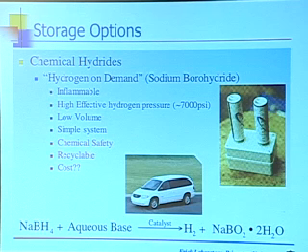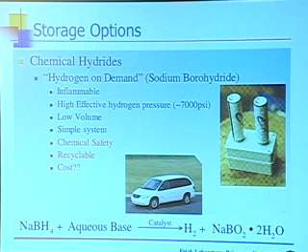On the other hand, if we went to this system, the bad news is, what are we going to do? We're going to have mountains of borax lying around at our corner stations because we have to empty this stuff out. That doesn't seem to make much sense. No, we need a way of taking that material and reforming it back into sodium borohydride. And it has to be energy efficient and cost efficient to do that. Although this part of the cycle, the part I'm showing you, works just fine, the recycle part has not been worked out well enough yet to be practical.